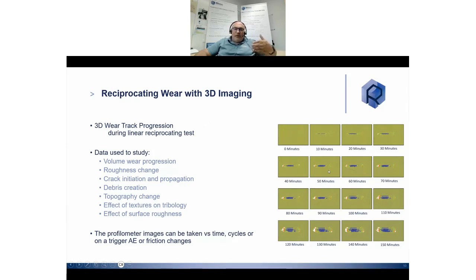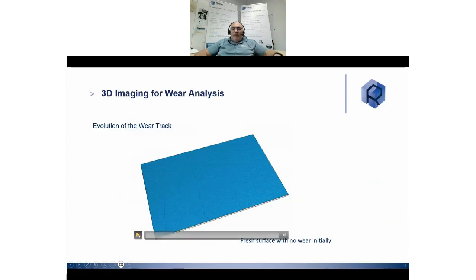It means you start with your linear reciprocating test, you move back to the microscope, you come back and you restart the test. With a 150-minute example here, we can measure the volume wear progression, we can measure the roughness change, we can check if we have crack initiation, debris creation, topography change. It gives you much more possibility than basically doing 150 minutes directly and analyzing at the end the full test.